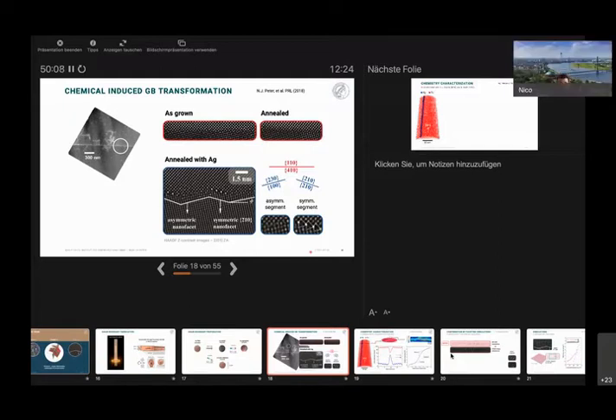Yes, so you brought up some very good points actually, in terms of how the elastic properties change and things like that. I believe it's not so much of a problem, because if you look at this slide here, at the structure of the asymmetric boundary, it is pretty, I don't want to say chaotic, but it has quite some room for adopting silver, for example, for bigger atoms, right? So I think the strains that you introduce might not be as severe as if you look at this perfect boundary here, where you replace distinct atoms on certain sites. There it might be more severe.